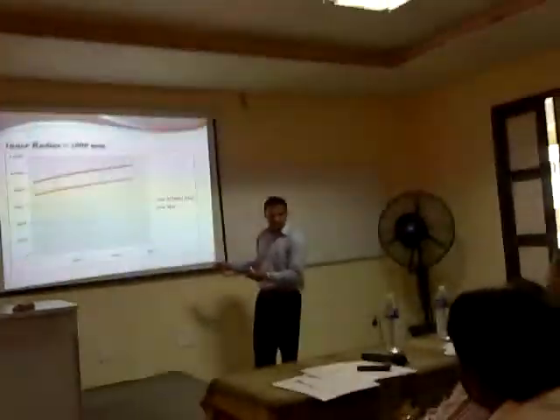So for a particular radius of 2000 mm, when I vary the half length, I am getting the stress value, and this variation in stress value diminishes as we go along increasing the half length. Same for 5000, and for 7000 we are getting almost a straight curve. Next.